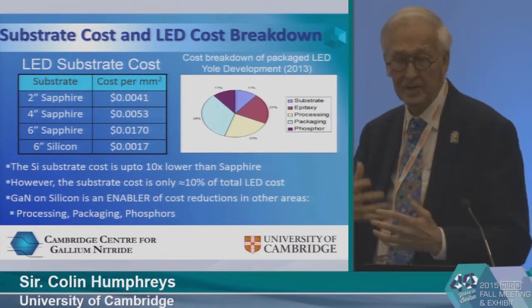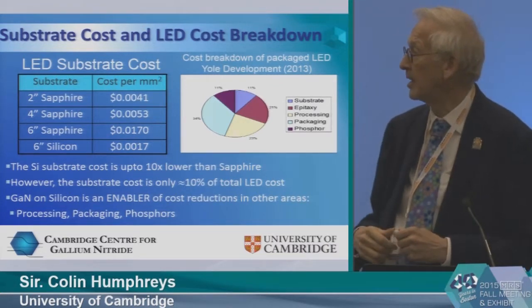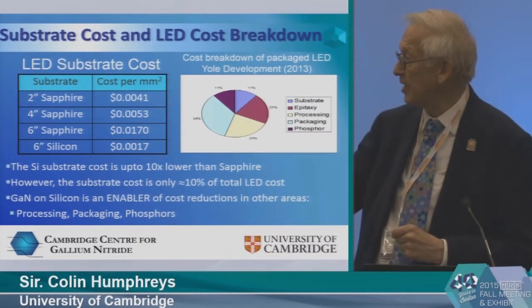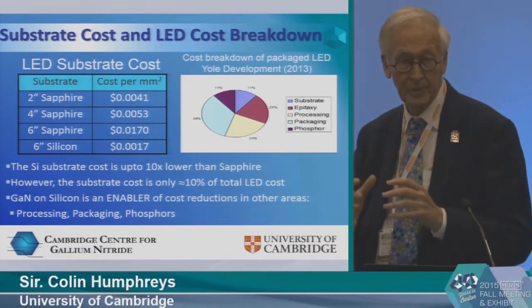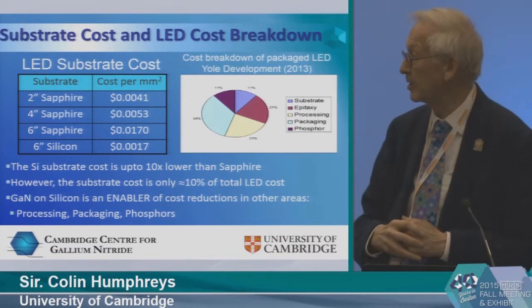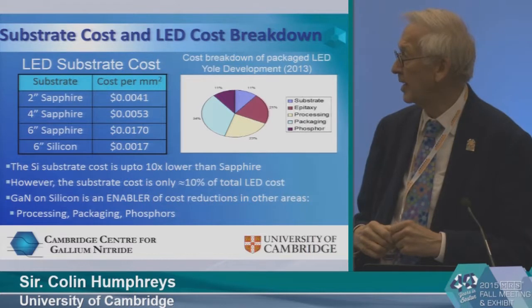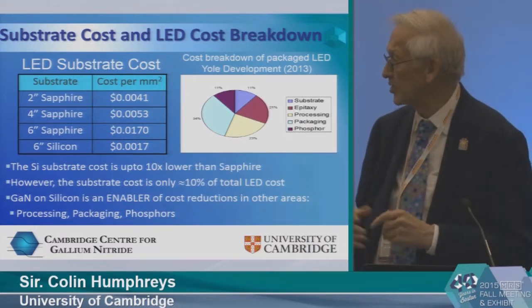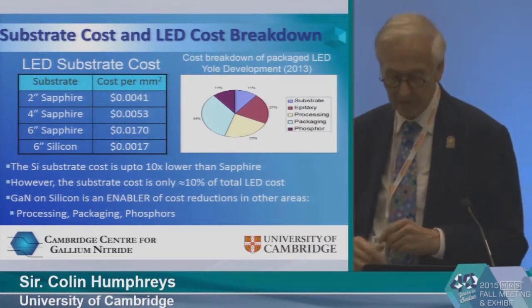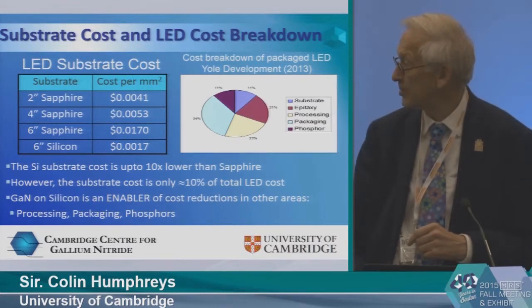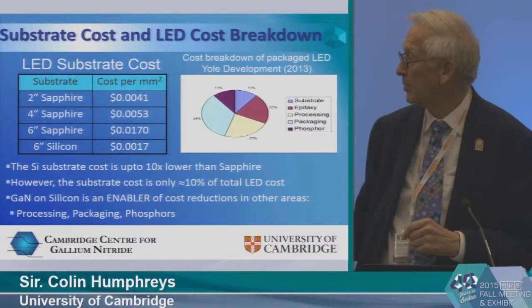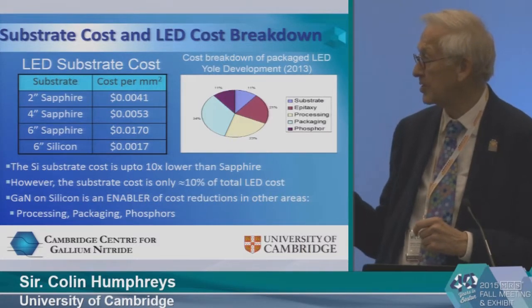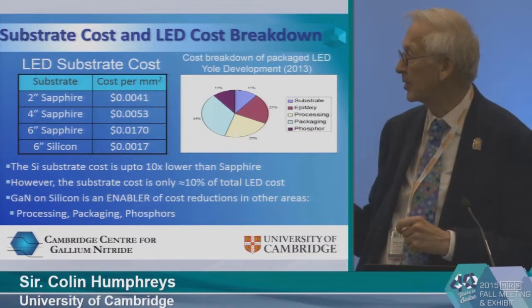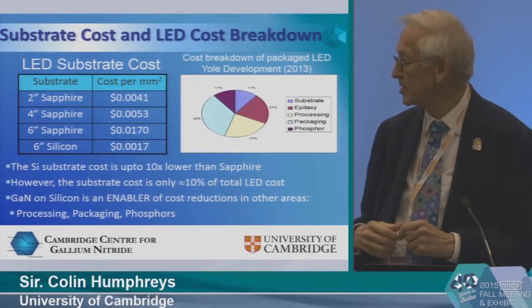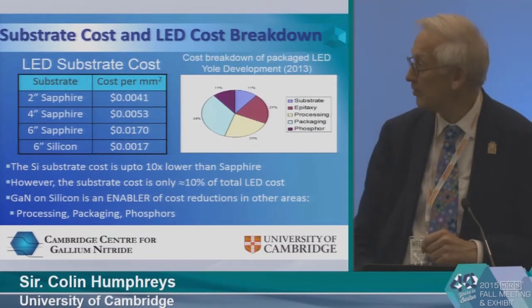And so you immediately get quite a large cost saving from that. The alternative is to try and grow on 6-inch sapphire, which again gives this reduction in unit cost. But you see, 6-inch sapphire is about 10 times more expensive than 6-inch silicon. So if you have 6-inch silicon, you improve the substrate cost and save about 10% of the total cost by doing that. But you get much greater savings, it turns out, because if you grow on silicon, you can then enable cost reductions in the processing, in the packaging, and also in the phosphors.